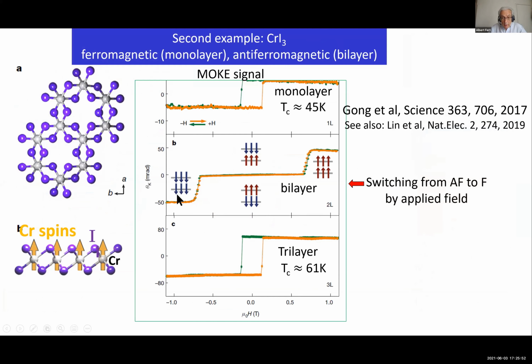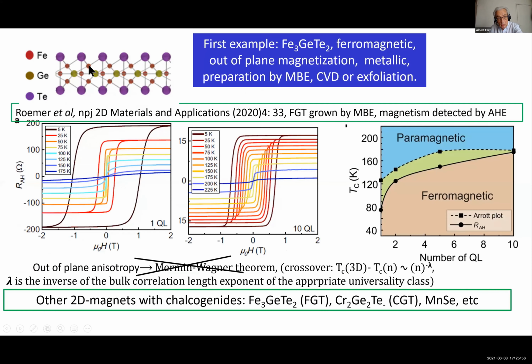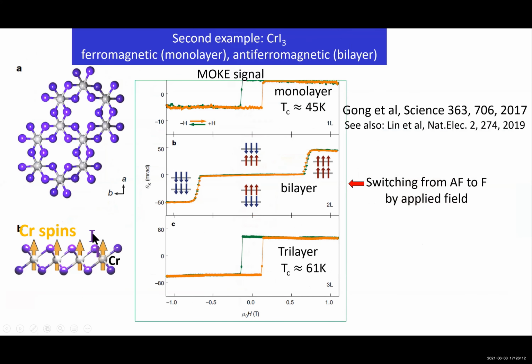So this is the structure. Again, I can show you the structure of the first one. You can see the third one, where there are germanium, tellurium, and iron. The spin-orbit coupling comes mainly from Te here. So now going to CrI3, you can see again the structure, and the magnetic moment is on the chromium.